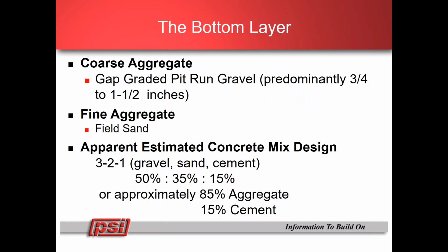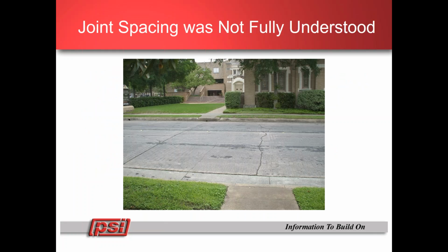The bottom layer was a gap-graded pit-run gravel local to the San Antonio area. The fine aggregate, a field sand, the apparent estimated concrete mix design of 3-2-1 is your basic concrete mix, 50% gravel, 35% sand, 15% cement. While joint spacing was not fully understood, we see some transverse cracks in this particular picture.